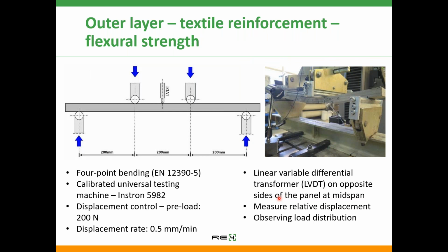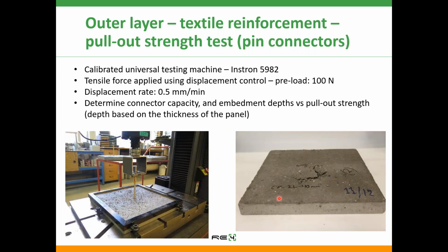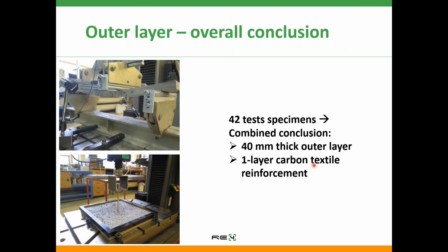Here you see how it looks. This is 4-point flexural strength, also measuring the displacement. In the pull-out test, you test how much strength you need to pull out a connector, and then you assess the damage done. I will not say too much about this, other than that from these 42 test specimens and these 2 tests, our conclusion was that we should go for a 40mm thick outer layer as shown previously, and 1 layer of carbon textile reinforcement. So this is what we could provide to CREAG for their upscaling.